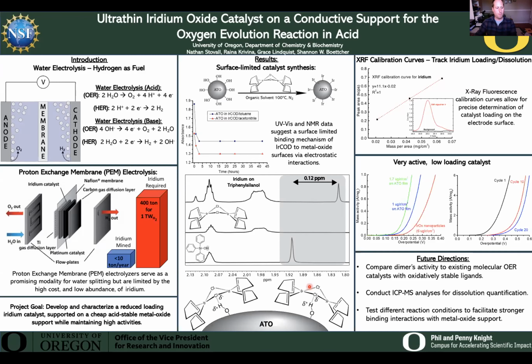Cool. This likely could be due to the weak binding interactions of our iridium dimer to the surface hydroxyl groups.